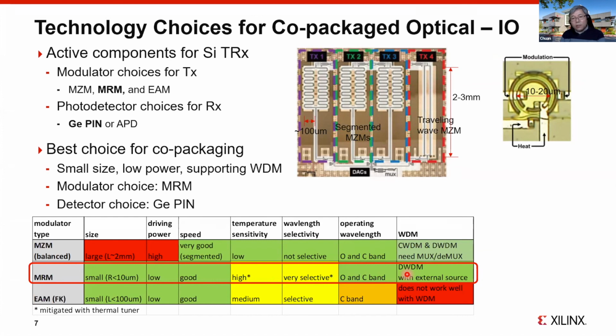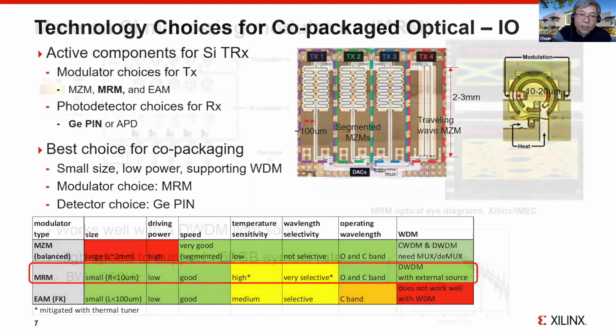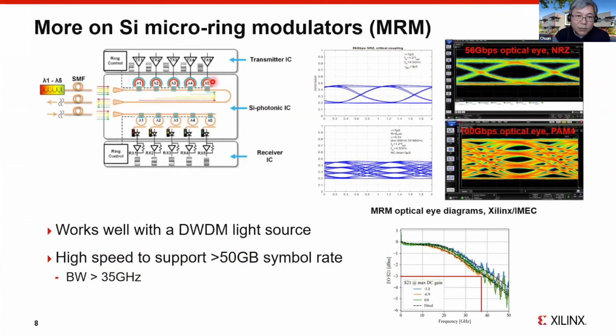And another limitation here is crosstalk. On this plot, you have these individual modulators modulating individual laser lines coming in, right? But the modulator itself has a Q factor, which is not infinitely big. Actually, for high speed, that Q factor has to be relatively low, maybe around 4,000, 5,000. That means each modulator will have a tail. Each modulator can also modulate a laser line that comes close to its resonance wavelength. Therefore, in order to avoid crosstalk, you need to set a minimum separation between channels. So given these two, you have a bounded number of channels you can support.